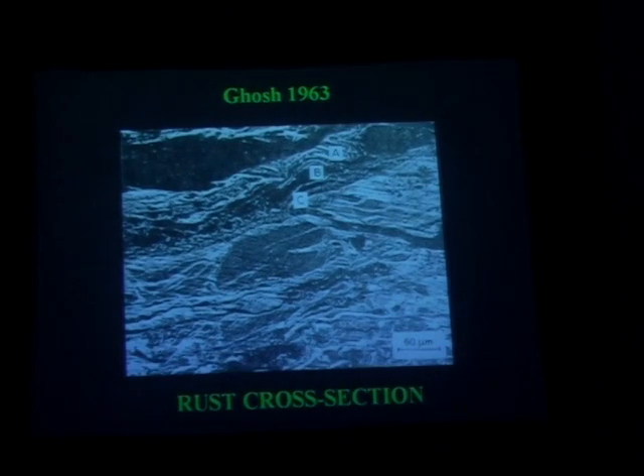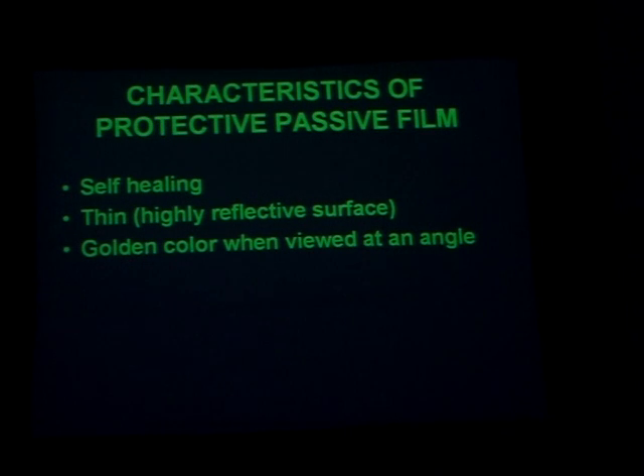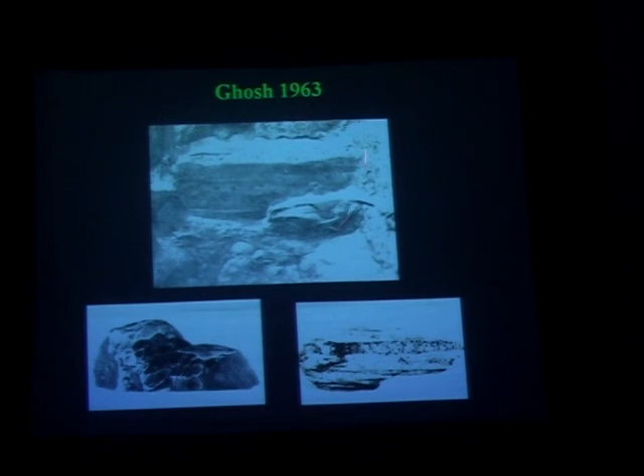What is the proof of that? 1963, you can see the microstructure. What are the characteristics? Self-healing. You see in 1963, they took a piece of iron from the iron pillar. And you can see in 1993, you don't even know where the cut was taken. Also, look at the place I took in 97 and 98, it's completely healed. And of course, thin, very, very thin passive film. Look at the reflection on the surface.